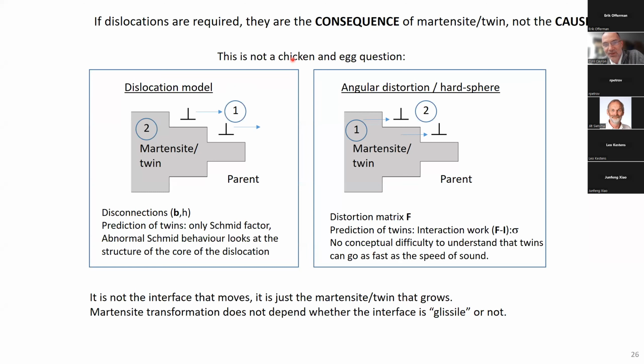And it's not a chicken and egg question. Because if you go in the other direction, you need to explain the dislocation to explain the martensite. And it's quite complex, I should admit. There are some people that spend part of their life on it, but I don't. So I prefer to say first we have martensite, and maybe we need dislocations to accommodate the interface between martensite and the parent phase. But here the calculations are easier because, as I will show you, we can predict the twins of the martensite by using the interaction work.